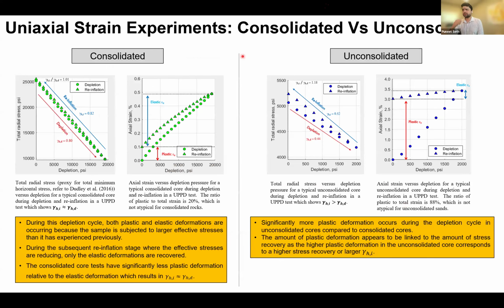Okay, so just to explain what was observed in these tests, I'm going to use one example from consolidated and one from unconsolidated. The plots that you see here basically show stress on the Y, depletion on the X, strain on the Y, depletion on the X, and the same for the unconsolidated sample. So what we see in the case of the consolidated sample, the stress change during depletion and reinflation. Sorry, depletion is these circles and reinflation is these triangles.